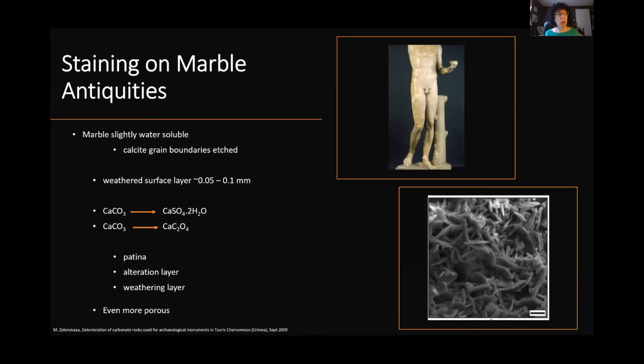And so what's sometimes called the patina on an ancient marble, or the alteration or weathering layer, is in fact quite porous. What we're looking at on the bottom right is the layer of gypsum crystals that forms on the surface of ancient marble. And you can imagine if an organic coating is applied to an ancient marble, as they always are, how that coating would get stuck in those porous crystals and be nearly impossible to fully remove.